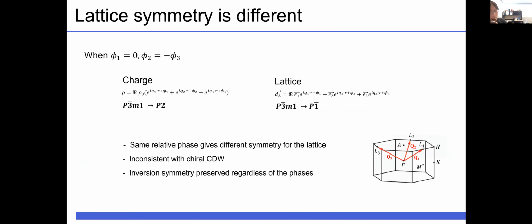But however, unfortunately, this simple model cannot explain everything. There is another problem, which is that the symmetry of lattice and charges are different. In a previous slide, we created a chiral CDW with different phases. Let's bring the same argument to the lattice. We can sum phonon eigenvectors at 3 L points with different phases. And of course, because lattice displacement cannot be imaginary, we need to take the real part.